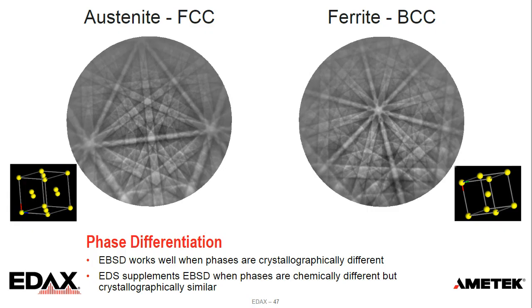They're very distinct crystallographically. So what that means is that the projection, the planes that diffract are different. The projection of those planes onto the EBSD detector are different. For EBSD, for our Hough-based indexing, we're measuring the angles between these planes. So if different planes are diffracting, angles are different. It's very easy to tell these different phases apart. When structures start to become more crystallographically similar, that's when EDS can supplement EBSD.